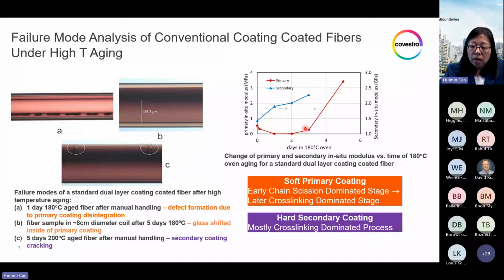Another important observation is that after 5 days of 180-degree aging, the coating layer can no longer be easily stripped off. It was very hard to strip off, which means the primary coating is no longer a soft gel as it was after the first day. It turned into a harder material. This can be clearly seen in this chart following the in situ modulus change of the primary coating during aging. The red line started at a normal modulus level of around 0.6 megapascal, dropped severely in the first couple of days to near zero, which means it is very close to liquid, then rose a little bit on the third day, and then rose sharply after 5 days.